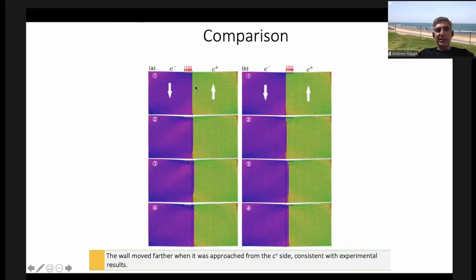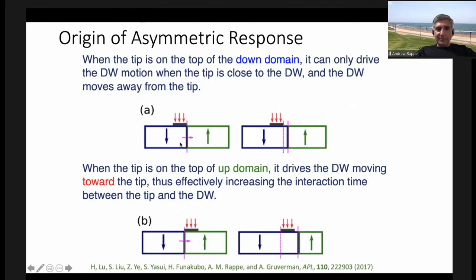These are snapshots from that molecular dynamics movie. So this is all done at finite temperature. I could tell you more about the methodology to the extent that you're interested. And so the conclusion is that the wall moved farther when it was approached from the C plus side, consistent with the experimental results. And so we think that when the tip's rastering from the C plus side, it spends more of its time pushing from the C plus side. And so that gives you more domain wall movement. And so that is our model of the experiments.